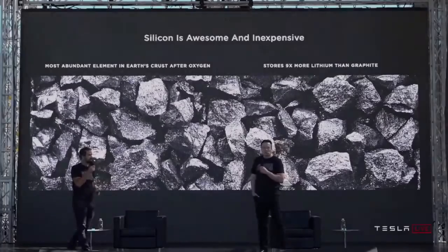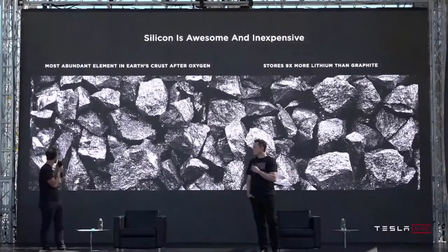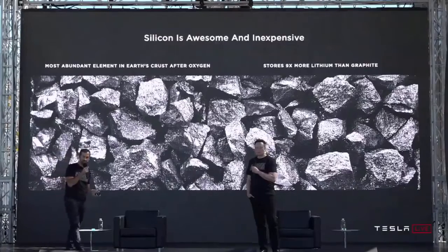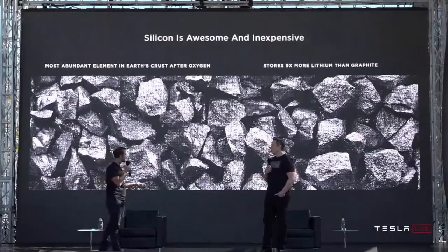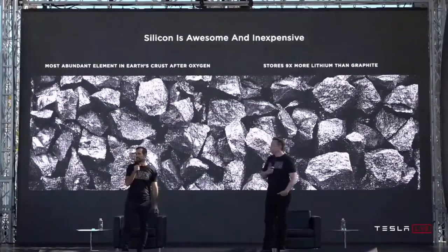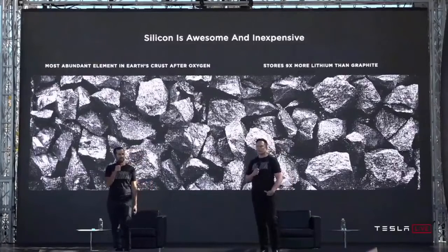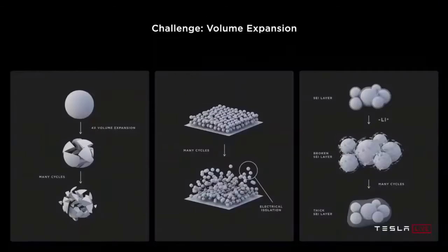Let's talk about silicon. It's the most abundant element in the Earth's crust after oxygen. And it happens to store 9 times more lithium than graphite, which is the typical anode material in lithium-ion batteries today. The challenge with silicon is that it expands 4x when fully charged with lithium. And basically, all of that expansion stress on the particles starts cracking, they start electrically isolating, you lose capacity, the energy retention of the battery starts to fade.